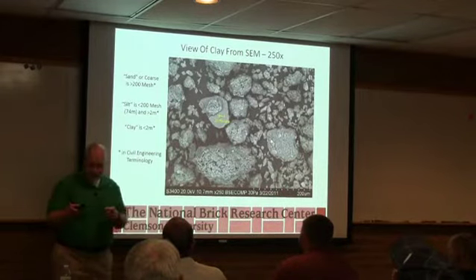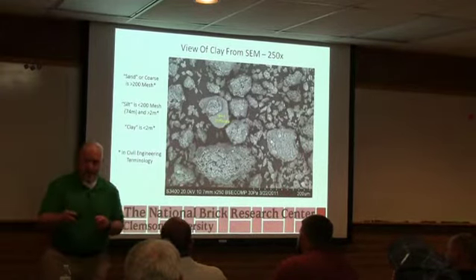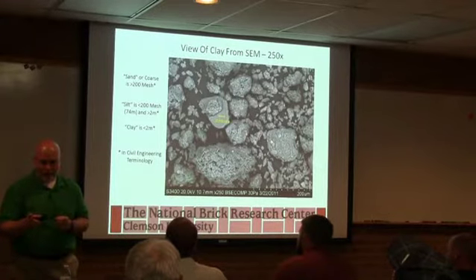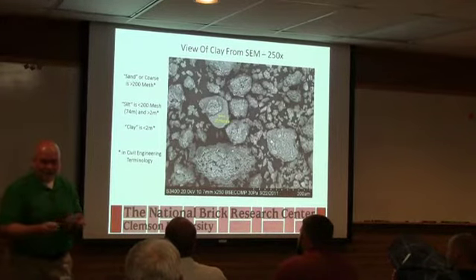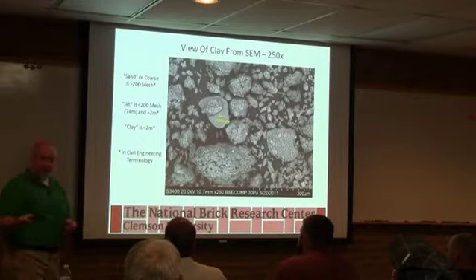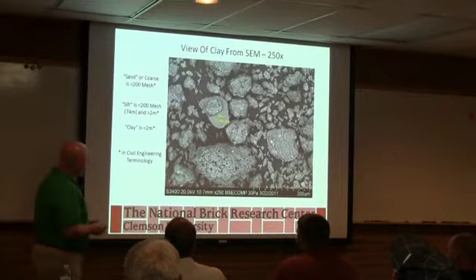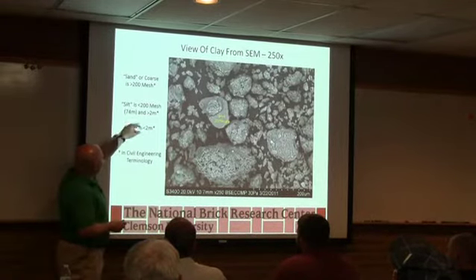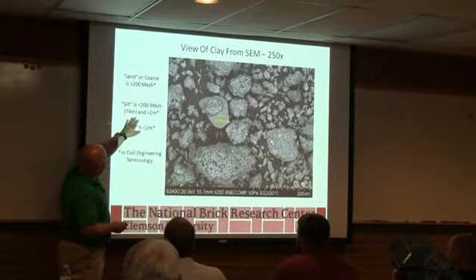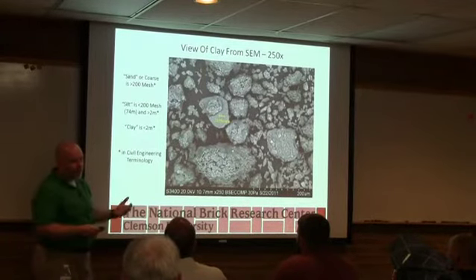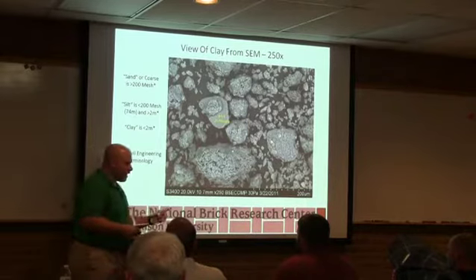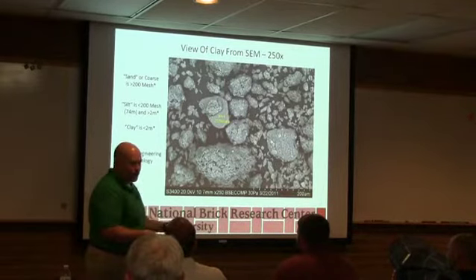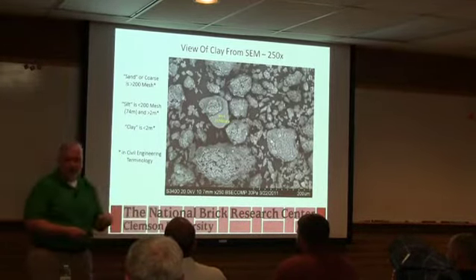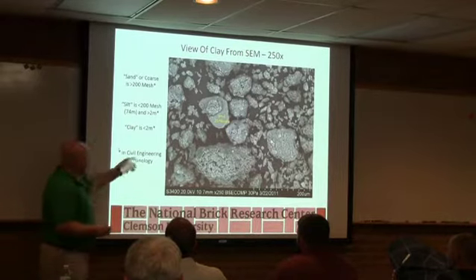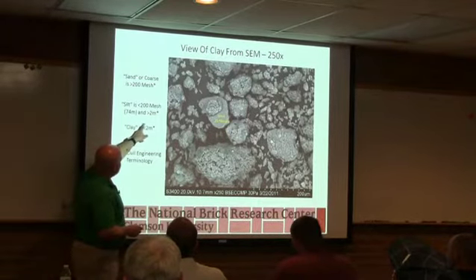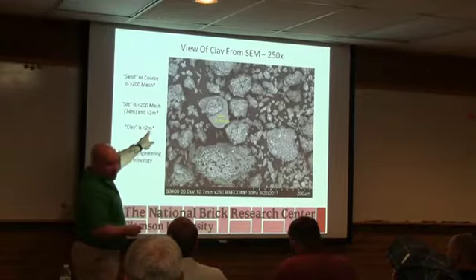Now, I believe here when you do particle size, you make a break for silt at 20 microns? Yeah. Okay. Some people do that. That's common in Germany too. We happen to use 74 micrometers, or a 200 mesh screen. So anything that goes through a 200 mesh. If you've done particle size, 200 mesh looks like a piece of cloth. You can't really see the individual openings. It's pretty small. And then anything that's less than 2 microns we call clay.